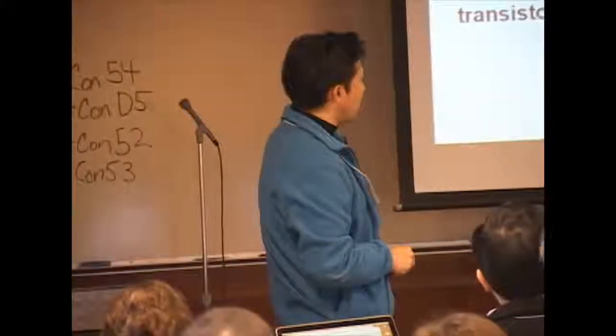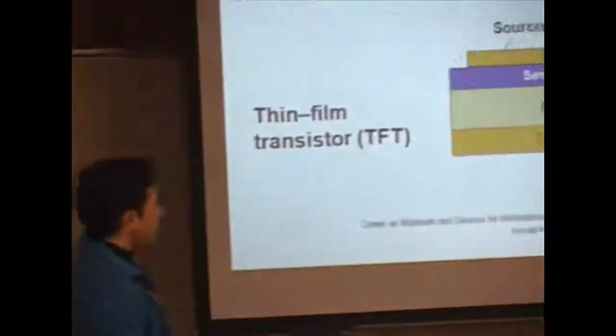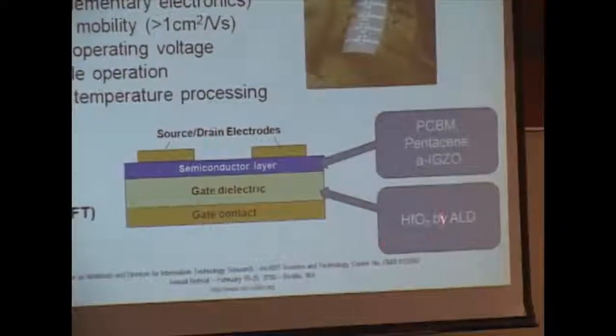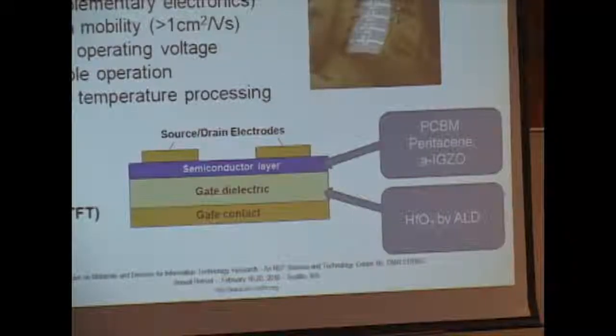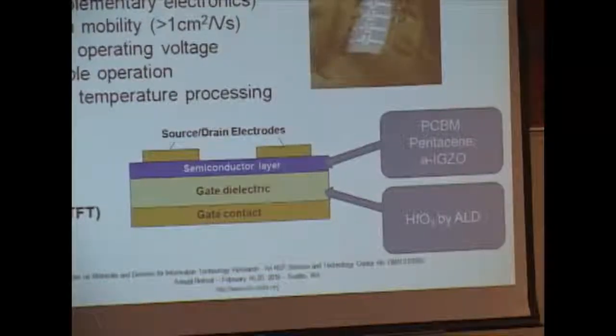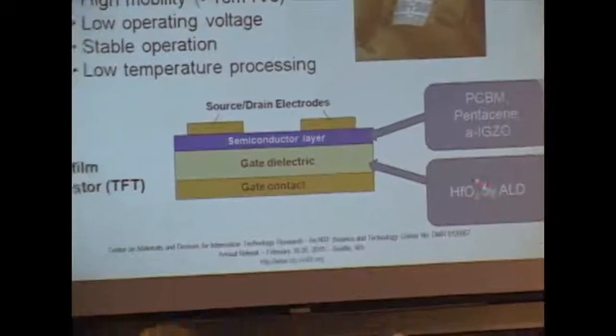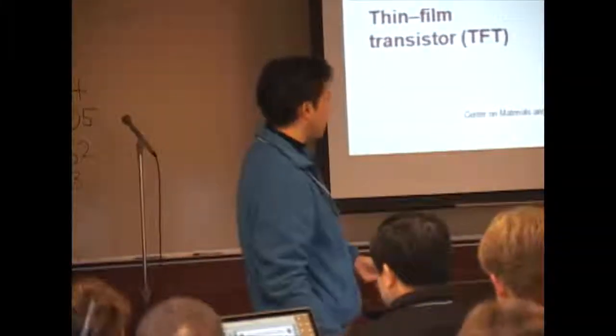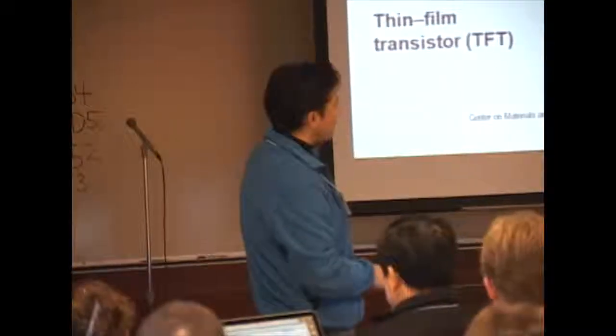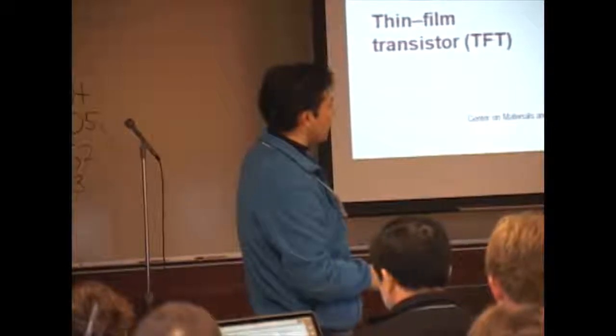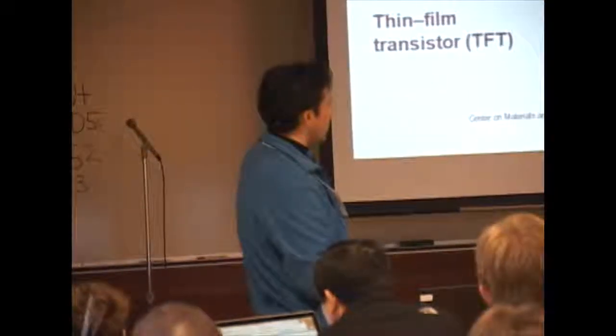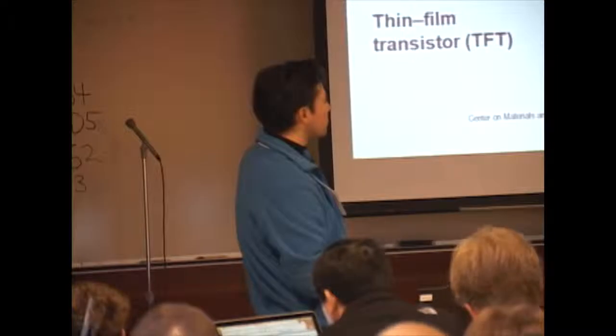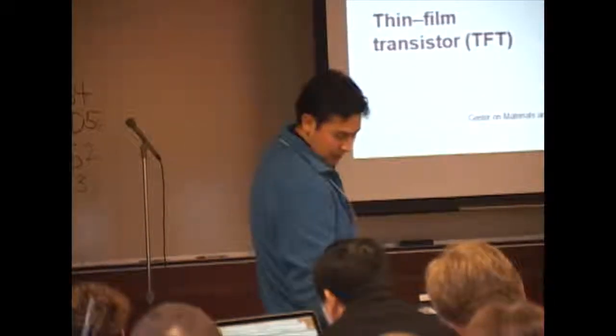What I'm going to talk about today is the use of hafnium oxide — mainly hafnium oxide deposited by atomic layer deposition. Hafnium oxide is a very promising dielectric now being implemented into regular CMOS technology, becoming an industry standard mainly because it has a very large dielectric constant between 15 and 20. I'll cover devices with hafnium oxide gate dielectrics, solution-processed PCBM devices, evaporated pentacene devices, and then oxide semiconducting TFTs.